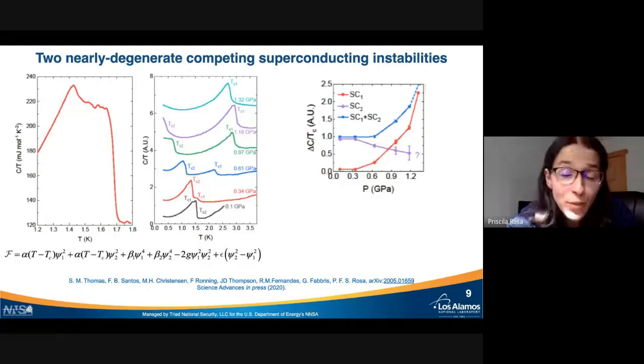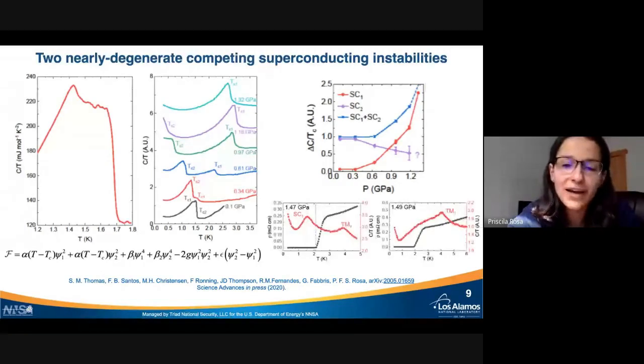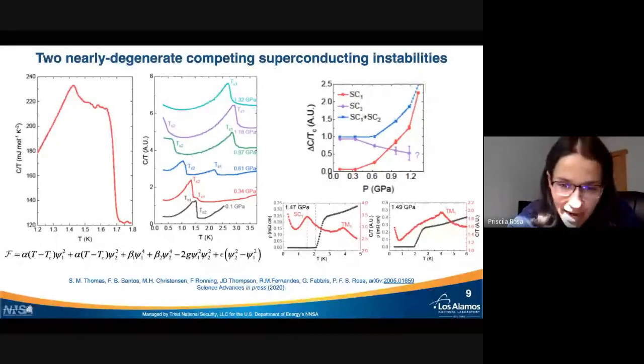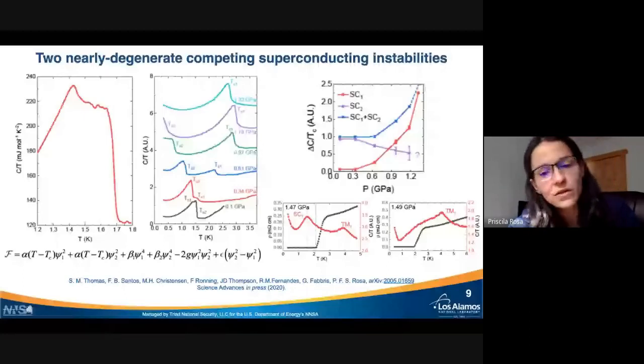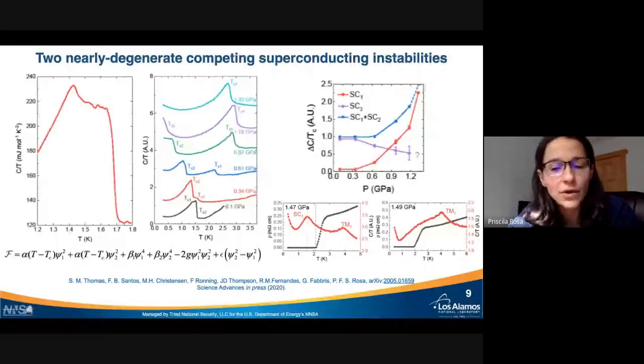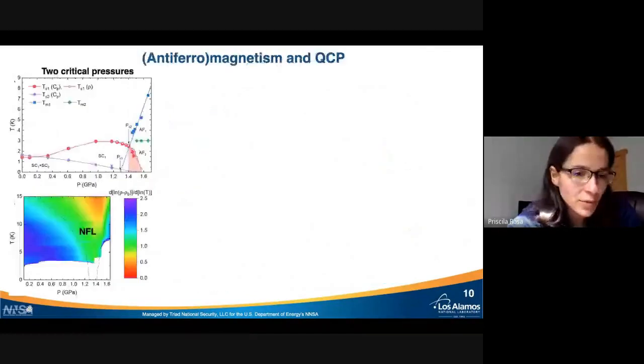But at higher pressures, it actually starts to deviate from what we would expect. And this could be because of a nearby magnetic instability. And fair enough, at higher pressures, indeed, we see evidence for the emergence of magnetism, even though we don't have spectroscopic measurements yet. This is consistent with antiferromagnetism.